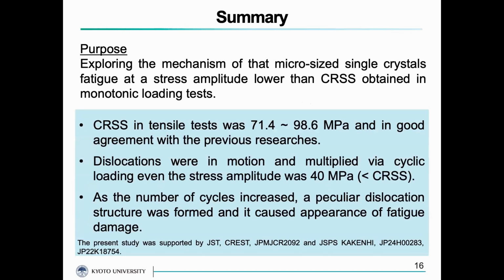In this study, to explore the mechanism of how micro-sized single crystal fatigues at stress amplitude lower than CRSS, we conducted tensile and cyclic loading tests on micro-sized nickel single crystal. The CRSS in the tensile test was in the range between 70 and 100 megapascal and in good agreement with previous research. And in the cyclic loading test, dislocations were in motion and multiplied by cyclic loading, even though the stress amplitude was lower than CRSS. And as the number of cycles increased, peculiar dislocation structures were formed, and this caused the appearance of fatigue damage.